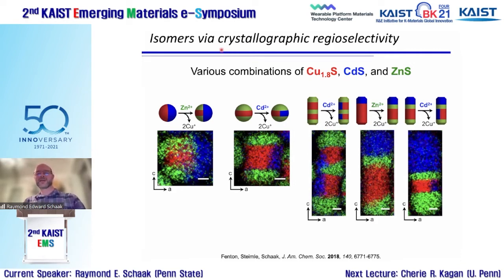The other thing is making this analogy to the synthesis of molecules. These reactions are regioselective. They're targeted to certain regions of the nanoparticle that are driven by crystallographic relationships. So essentially, this is crystallographic regioselectivity. It's using crystal structure to define the precise locations within the nanoparticle where the cation exchange reactions are happening.